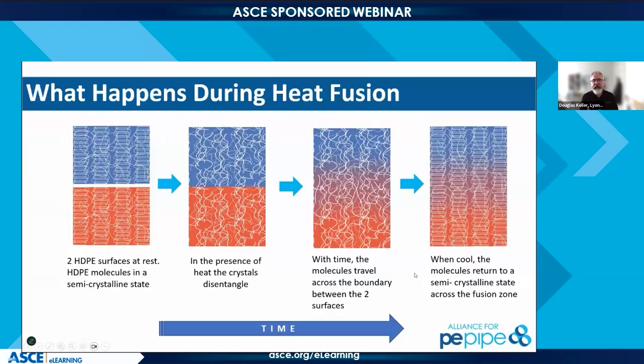So what happens during the heat fusion step? Well, polyethylene is a semi-crystalline material. For high density polyethylene, it's roughly 60% crystallinity, and the crystal section is a regularly ordered crystal structure. So it's very similar to metallics that have a crystal structure to them. In between those crystals, which is the little loops that are kind of tightly packed together, we have amorphous material. And I have an example here. If you think of these black and white sections as the crystalline phase, and then if you can kind of see there's Velcro here, that would be the amorphous phase.